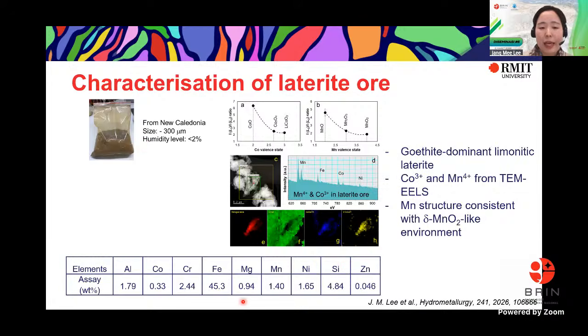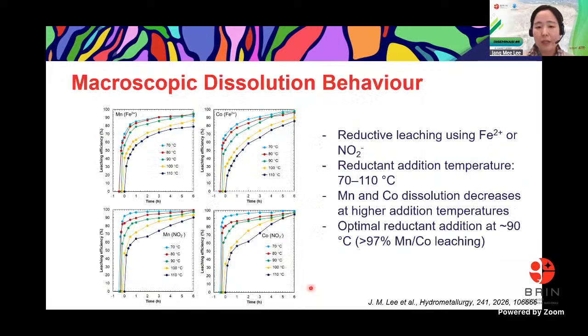And through the XRF characterization, this contains 0.33 weight percent of cobalt, iron is 45.3, manganese is 1.4, and nickel is 1.65. So this is just an overview of the characterization of the laterite ore.